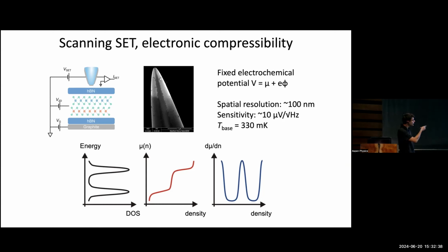What we can do is we can hook up a battery. We can apply a voltage to the sample that fixes its electrochemical potential, which is the sum of the chemical potential of the sample and the electrostatic potential. And so the electrostatic potential is what the SET is sensitive to. And we also have a backgate beneath the sample. As we apply voltage to the backgate relative to the sample, that changes the carrier density in the sample, which changes the chemical potential in the sample. And because the electrochemical potential is fixed, there must be a corresponding change in the electrostatic component. And that's what we're sensing with the single electron transistor.